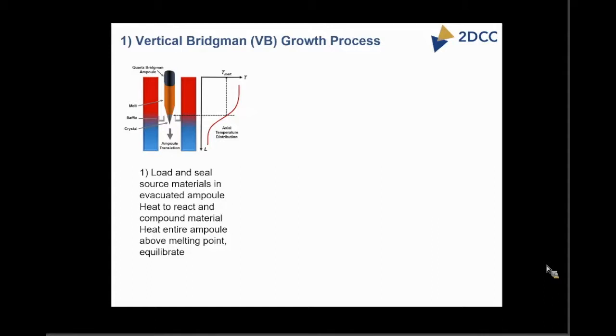So the first effort that we're setting up here in the 2DCC will be a vertical Bridgman crystal growth process. Basically, this process involves a crystal growth system in which you set up an axial temperature gradient with a hot zone and a cold zone. You typically load a source material in an evacuated ampule, typically in an elemental form. You go through a compounding step typically. You can either do this in situ or in a separate system.